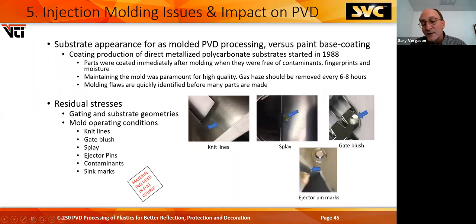Splay is moisture in the part. You can see these little ghosty lines. If you've got splay in the substrate, when you metallize it, you're going to have that splay appearance on the metal because it's a rough area. This is gate blush. Could be too high a pressure at the gate. It's hard to see here, but this is an ejector pin mark. The ejector pin actually pushes on the backside of the part, but they leave a little bit of a blemish that shows through once the parts are metallized.